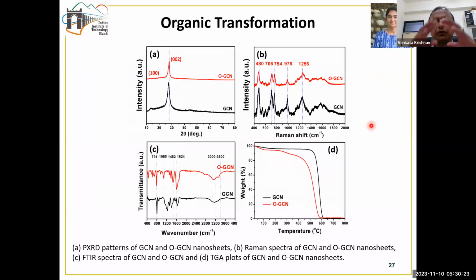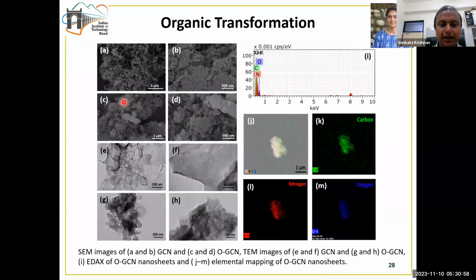And similar to the previous work, whenever we prepare a catalyst, we need to do a detailed characterization of the catalyst in order to understand whether the catalyst has the structure as we expected and what the morphology of the catalyst is. For understanding the structure and the thermal stability, we have done powder X-ray diffraction, Raman spectroscopic analysis, and also FTIR analysis, which indicates whether the material preparation is successful, what the crystalline nature of the material is, and what the different functional groups attached to this material are. And from the thermogravimetric analysis, we are able to figure out the thermal stability of our catalyst material. Subsequently, we have done the morphological studies using SEM and TEM.